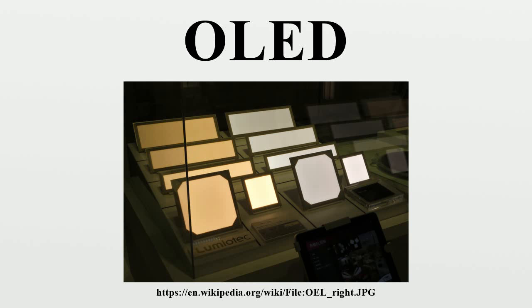A number of materials are used for their charge transport properties. For example, triphenylamine and derivatives are commonly used as materials for hole transport layers. Fluorescent dyes can be chosen to obtain light emission at different wavelengths, and compounds such as perylene, rubrene and quinacridone derivatives are often used. AlQ3 has been used as a green emitter, electron transport material, and as a host for yellow and red emitting dyes.